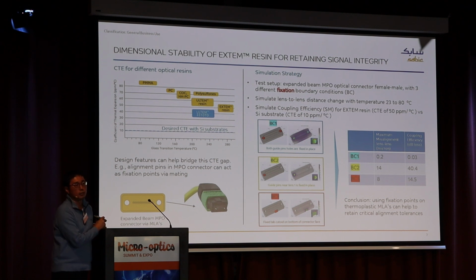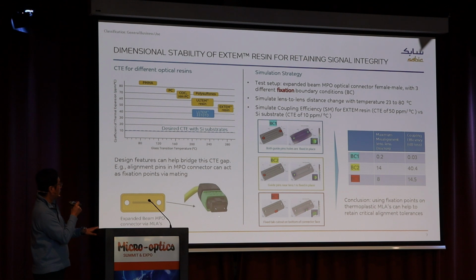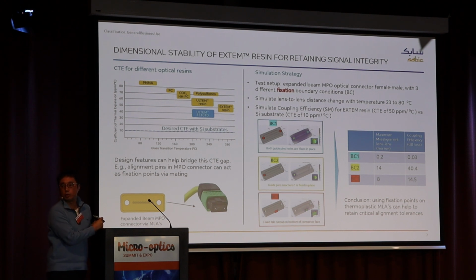But that's not the end of the story. Even though our material has higher CTE, you can mitigate it in other ways. CTE mitigation has a long history in mechanical engineering. For example, in this case, we did a simulation using this MPO type of connector. In MPO type connectors, there are 2 metal pins. So we added this kind of design feature. In this case, we have 12 micro lens arrays. Then we did a structural, thermal, and optical performance analysis. In this case, we assumed these 2 pins completely block the movement of these micro lens arrays.